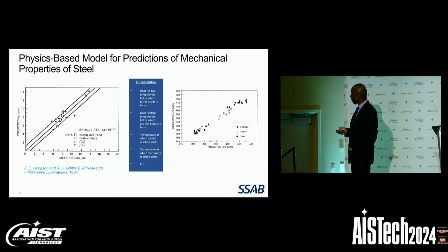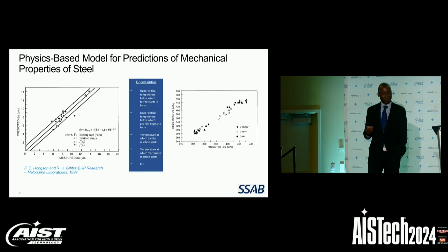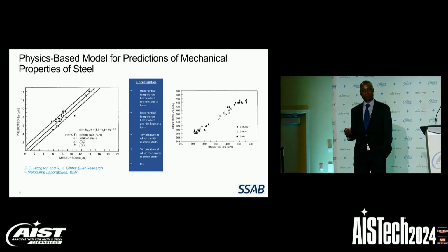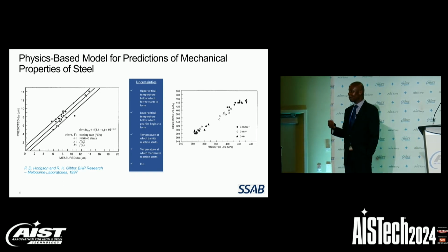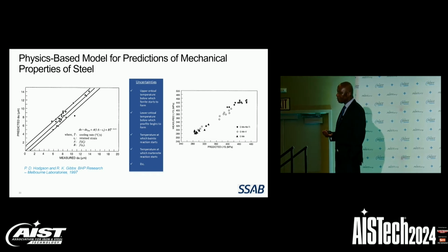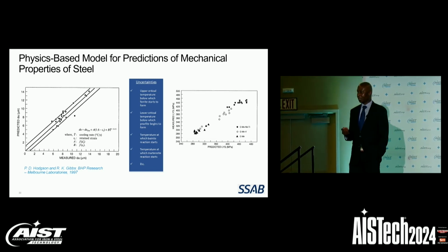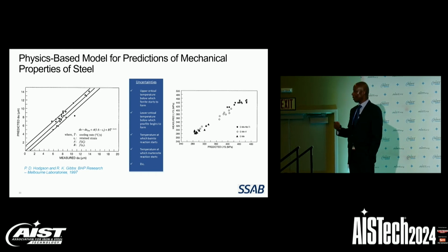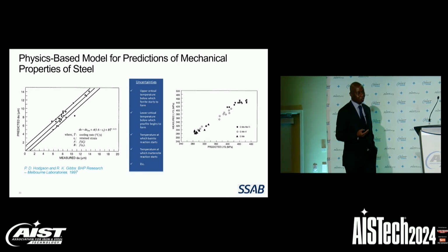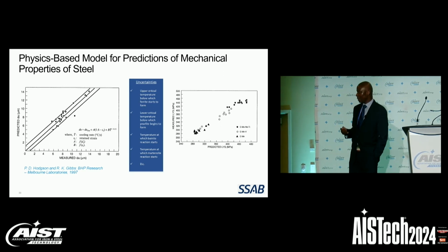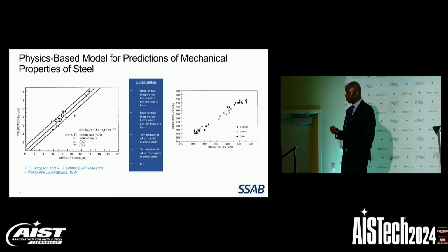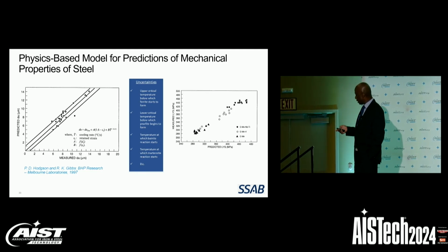But nevertheless, Hodgson and Gibbs developed a physics-based model for predicting the microstructure and mechanical properties of carbon manganese hot rolled steel. In their model, they considered microscopic phenomena along with their synergistic effect, but with huge assumptions. Their model is intended to predict microstructure and mechanical properties for carbon manganese steel where ferrite is the predominant microstructure. So hence, accurate determination of ferrite grain size is very important to the performance of the model.